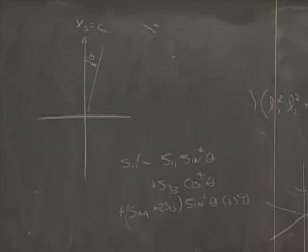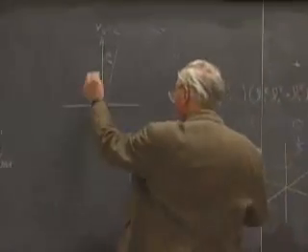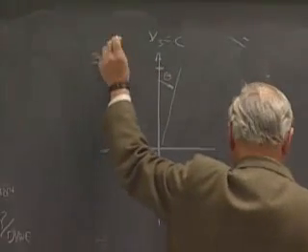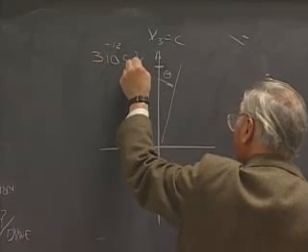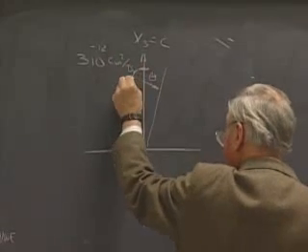So it's a fairly exotic surface, even as a surface of revolution. And what this looks like, it's something that peaks out at 3 times 10 to the minus 12 centimeters squared per dyne along the direction of C. It's something that comes down very sharply as you approach the normal to the c-axis.